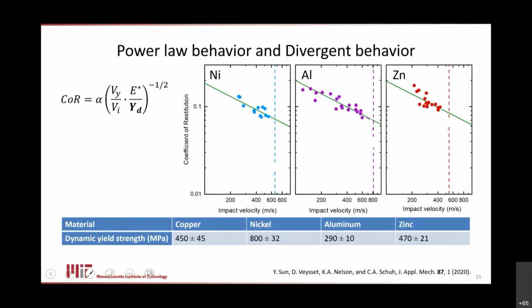So here they are for copper, nickel, aluminum, zinc. We've been able to fit and measure the dynamic yield strength. And again, just remember, this is a yield strength measurement at 10 to the 7th per second. So this is a range where there's no other mechanical test we could do to extract a number like this. So this may not be a perfect number, but it is quantitative and reproducible and has tight error bars.